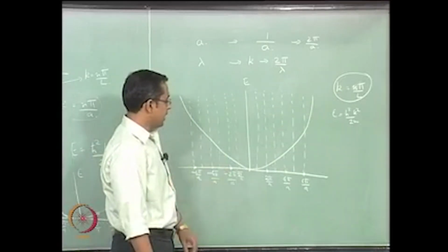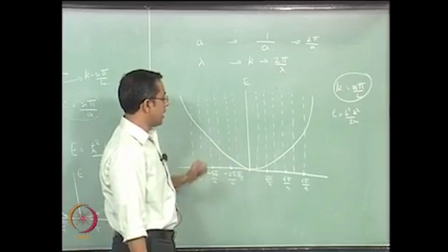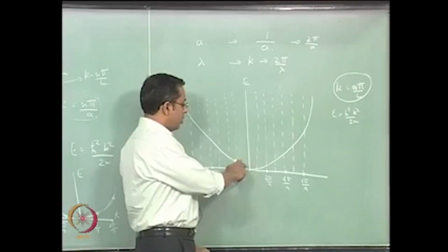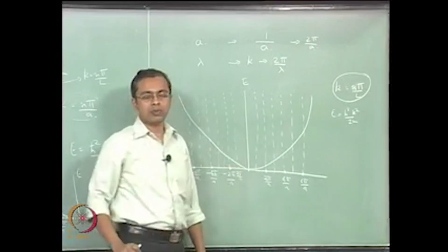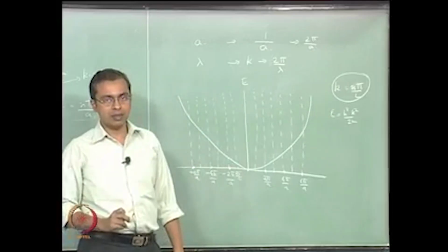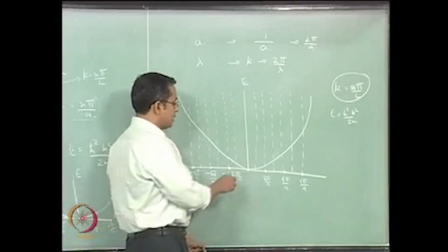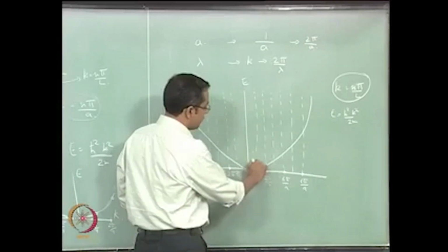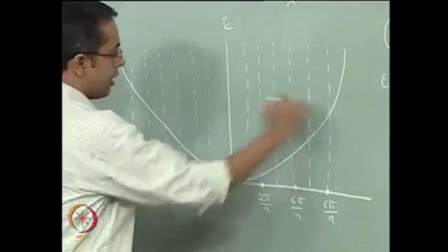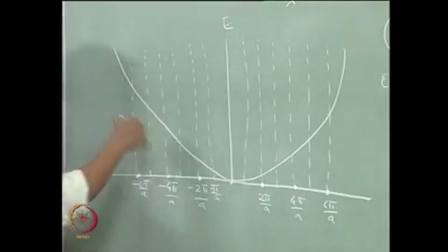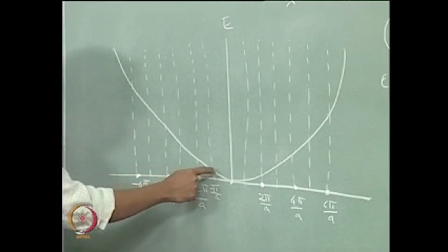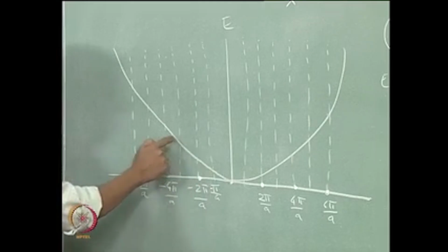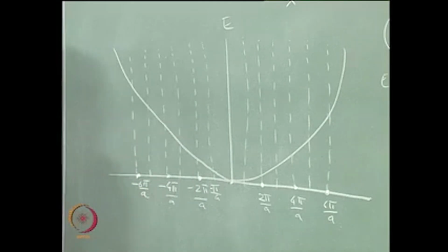We will conclude by saying that we have already seen that when the k vector touches the Brillouin zone boundary, diffraction occurs, therefore diffraction is occurring at all of these locations, because at all of these locations the k vector is touching the boundary of a Brillouin zone, okay.